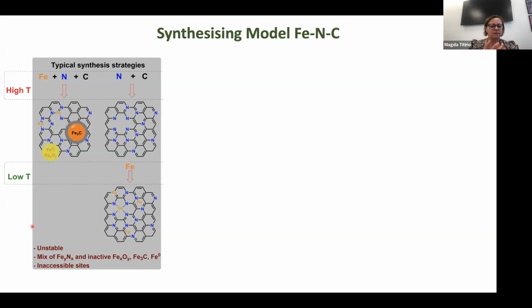In the literature, what most people do is they throw in a furnace an iron precursor, a nitrogen precursor, and a carbon precursor, and they hope that miraculously the carbon will be doped with nitrogen and the iron will be coordinated to these nitrogen sites. But in reality, when you do this directly at high temperature, you form a lot of different active sites. The iron you throw there would also form iron carbide. You can have some single atom sites, but also very easily you could form some metallic iron and iron oxide. So you don't have very well-defined active sites within this catalyst.